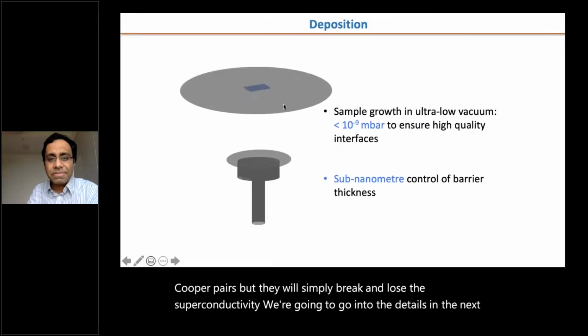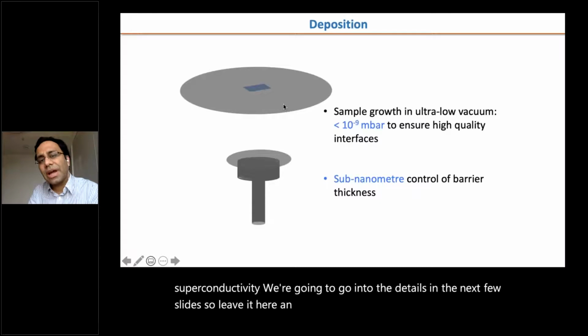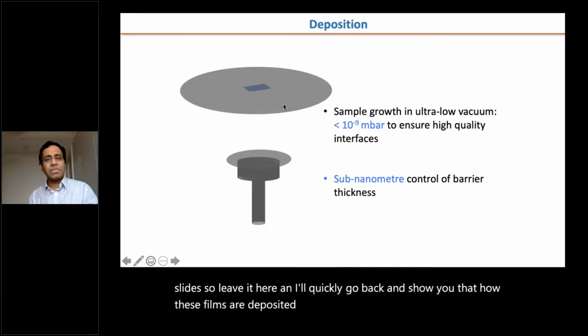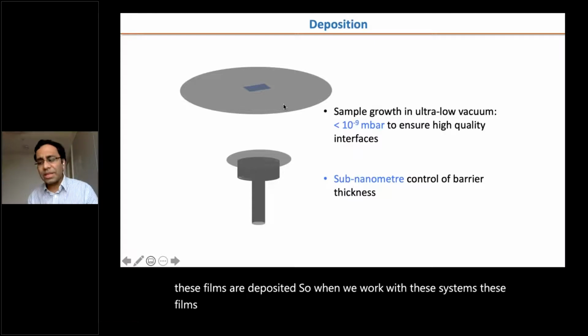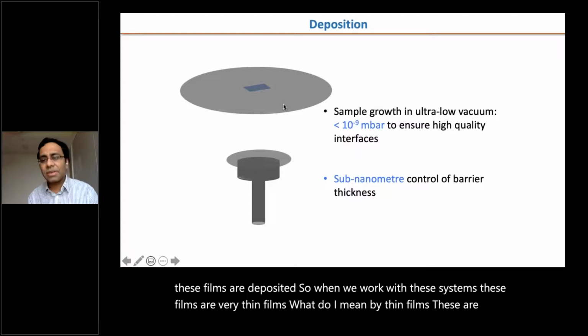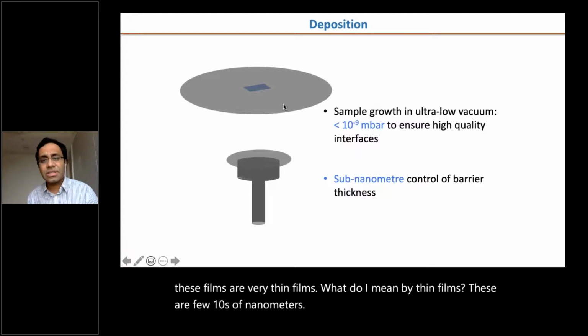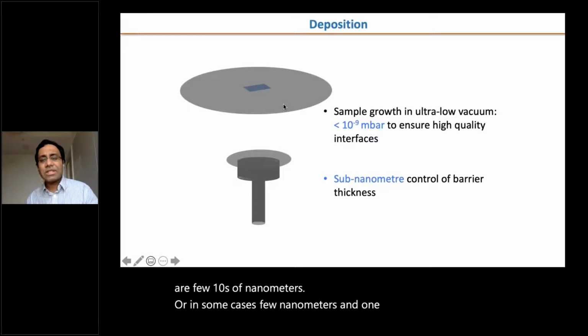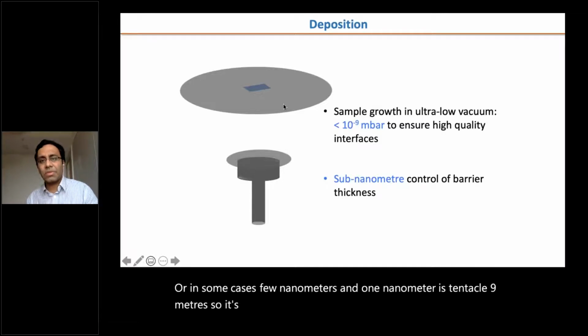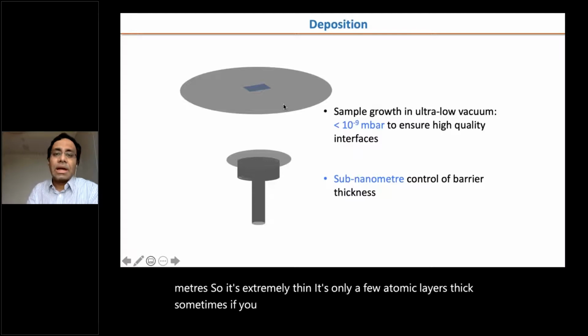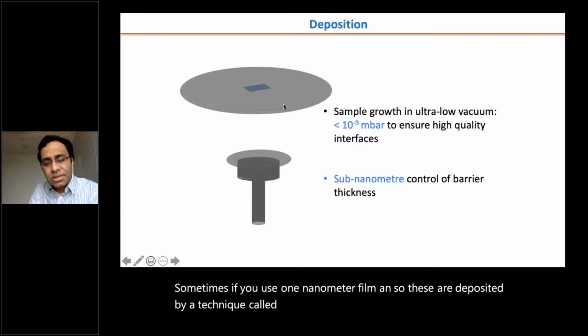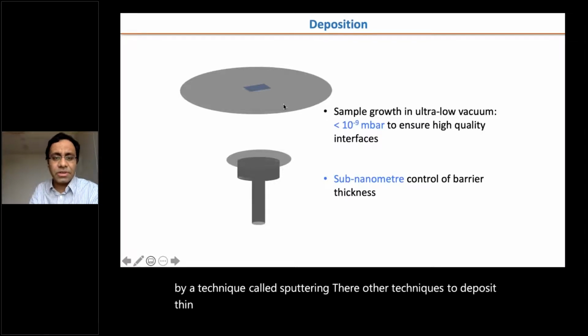So I'll leave it here, and I'll quickly go back and show you how these films are deposited. When we work with these systems, these films are very thin. What do I mean by thin films? These are a few tens of nanometers, or in some cases a few nanometers, and 1 nanometer is 10 to the power of minus 9 meters. So it's extremely thin. It's only a few atomic layers thick sometimes if you use a 1 nanometer film. These are deposited by a technique called sputtering. There are other techniques to deposit thin films, but we mainly use sputtering.